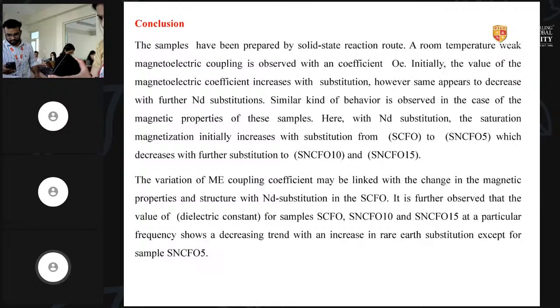the samples Sr3-xNdxCo2Fe24O41 have been prepared by solid state reaction route. A room temperature weak magnetoelectric coupling is observed with the coefficient alpha of 0.213 mV/cm Oe. Initially, the value of the magnetoelectric coefficient increased with the neodymium substitution.